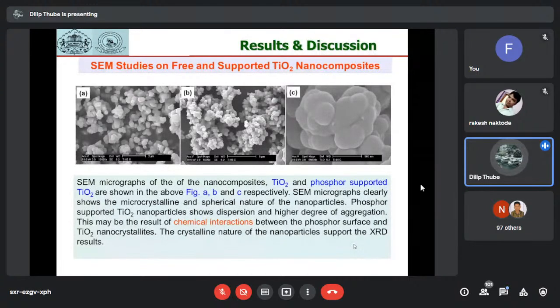Now, if you look at the surface properties of the materials, SEM and TEM studies have been carried out on free as well as supported TiO2 nanocomposite materials. Slide picture A shows free TiO2 materials, as well as picture B and C shows the SEM images of phosphor supported TiO2 materials, which clearly indicates that there is an aggregation of the TiO2 nanoparticles on the surface of a phosphor material. There is a dispersion and higher degree of aggregation, which may be because of the chemical interactions between the phosphor surface and the TiO2 nanocrystallites.